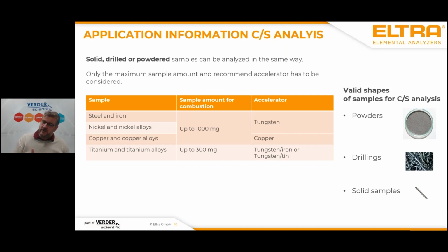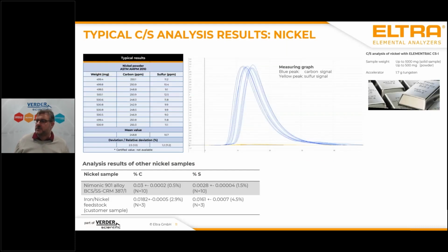On the left side of the table, you see our typical matrices, which means steel, iron, copper, nickel, and titanium. The only thing which is important is the maximum amount you have to apply to the crucible, which means 1,000 milligrams for steel, or maybe 300 up to 500 milligrams for a titanium-based sample. And that's it. You just apply your accelerator, start the analysis, and that's it. To give you an idea about typical results, we have nickel powder, which was analyzed in an ASTM test cycle. We get this powder, put it in our crucibles, add the accelerator, just 1.7 gram of tungsten, put it on the pedestal, and run all these samples.